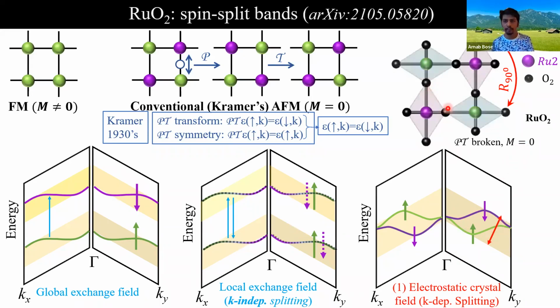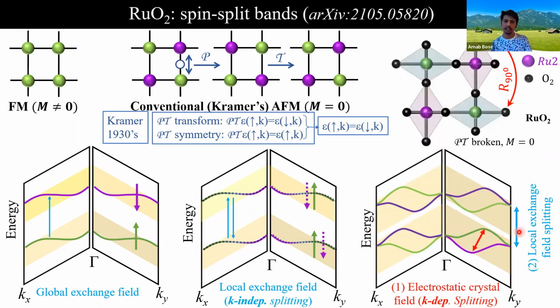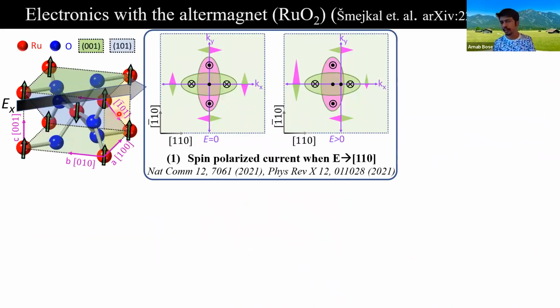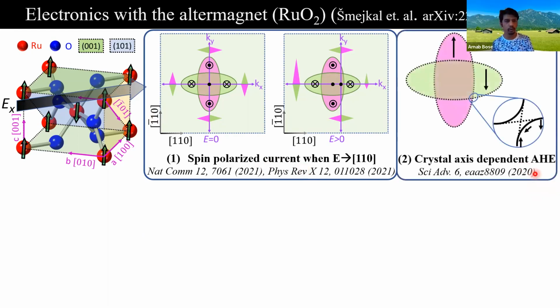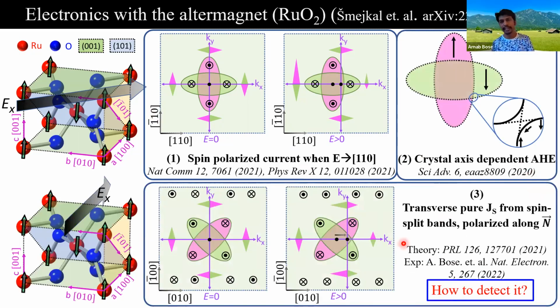Now, due to the local magnetic ordering, for the higher energy, we'll have alternate copies of this band. So it is also sometimes referred to as an altermagnet. We'll see that these spin split bands have tremendous influence on the electronic transport properties. For example, when we run electric current or electric field along a certain crystal axis of ruthenium dioxide, it can create spin polarized current. And it is predicted to generate GMR and TMR effects even in antiferromagnetic junctions. In presence of spin orbit coupling, it can also exhibit crystal axis dependent anomalous Hall effect as predicted here. The third possibility is that even in the absence of spin orbit coupling, it can still produce transverse spin current, just the way platinum creates transverse spin current from the spin Hall effect.